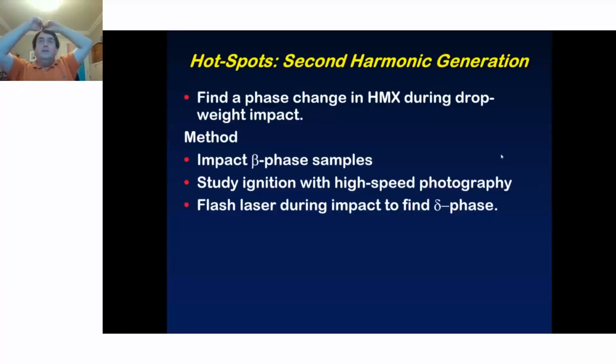Now, there is also another factor here. If you take HMX and make a polymer bonded explosive, or you've got a compact of HMX, and you drop it or hit it or otherwise introduce some kind of mechanical force onto the system, depending on how much force and for how long, you can produce delta phase within the HMX. The delta phase is quite impact sensitive.